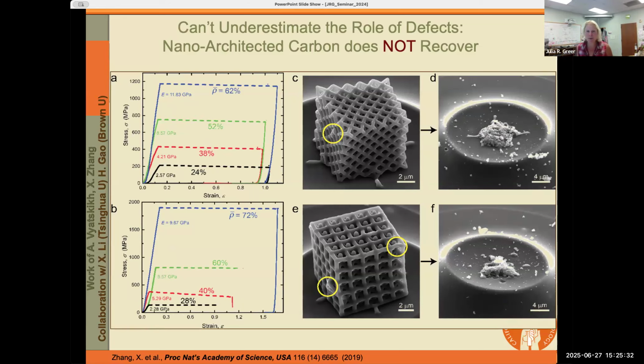What we're comparing here is an isotruss lattice, which is supposed to be the stiffest and the strongest, to an octet lattice, which was very stiff, and at every relative density, every time, they brittly failed. And the reason for that, of course, is again because we can't underestimate the role of defects. So here, what we're learning is that even when the individual nanoscale building blocks are deformable, you can't simply go and start architecting with them because you're going to have to worry about the structural defects.